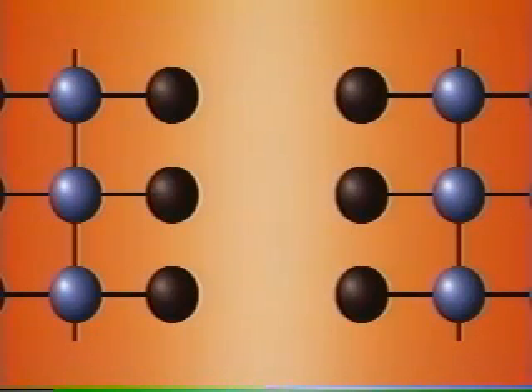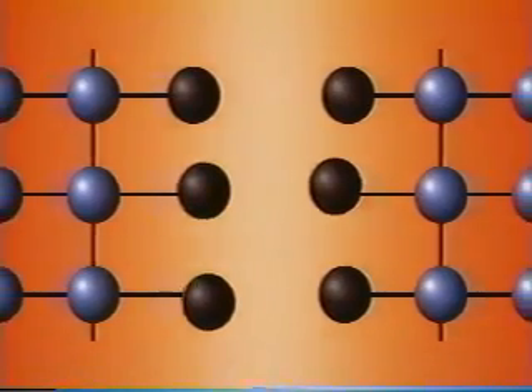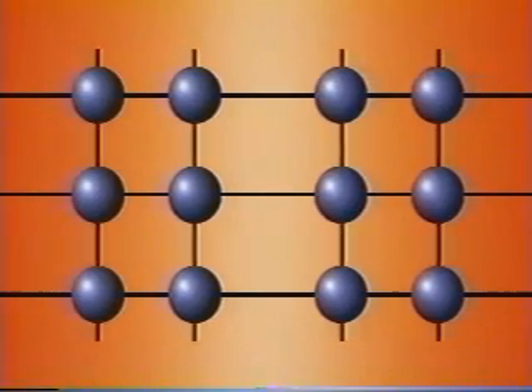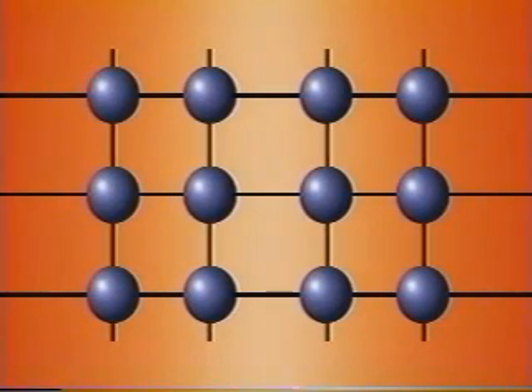This is an enlarged schematic of the welded face. The contact condition is local at first, but the area of metallic contact is rapidly enlarged by pressure and heat. Crystals across the welded face are generated around 800 degrees Celsius, and the two rails are metallically welded to each other.